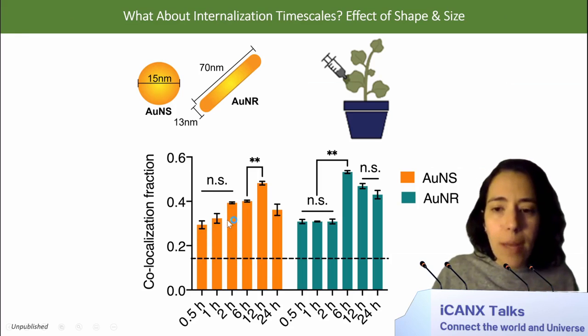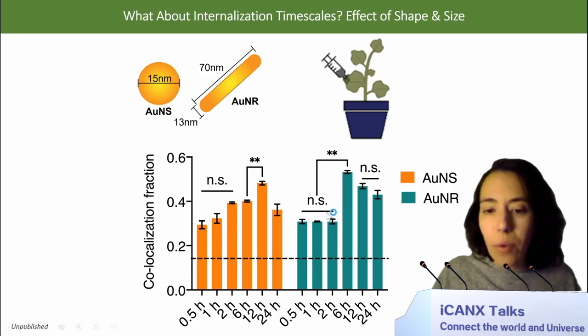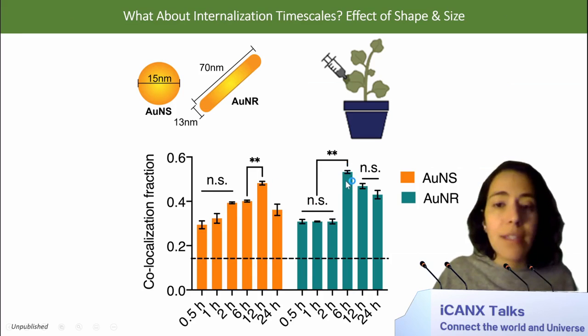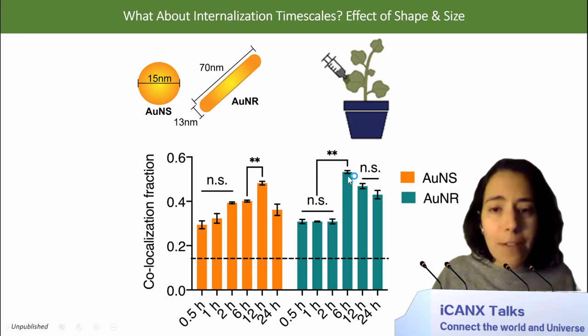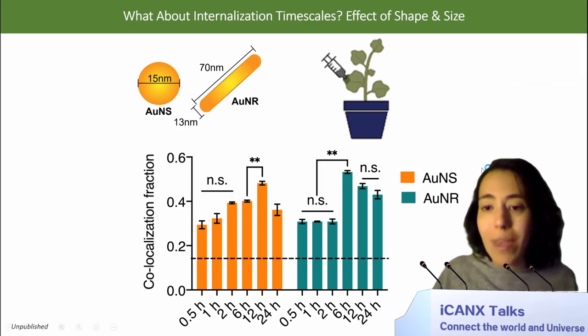So for example, these gold nanospheres internalize quite slowly with an apparent peak internalization 12 hours post-infiltration. Conversely, gold nanorods seem to have a very sudden internalization that peaks at around 6 hours post-infiltration, so much faster than the gold nanospheres, again, despite the aspect ratio being the main difference here. So some ongoing modeling studies in my lab to help understand these phenomena, and again, with the motivation of being able to understand these properties so that we can develop better technologies in the future.